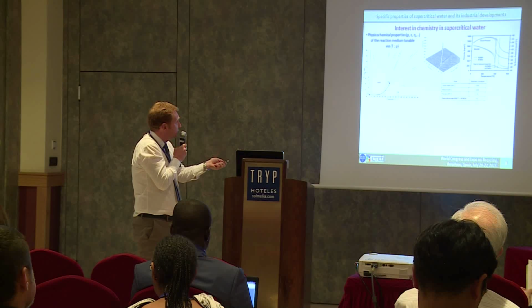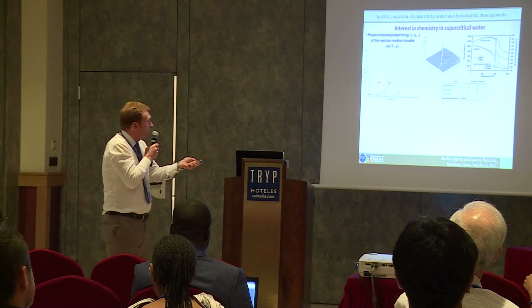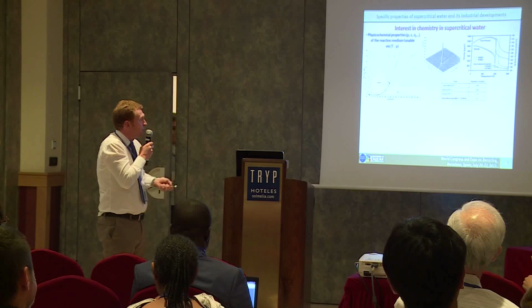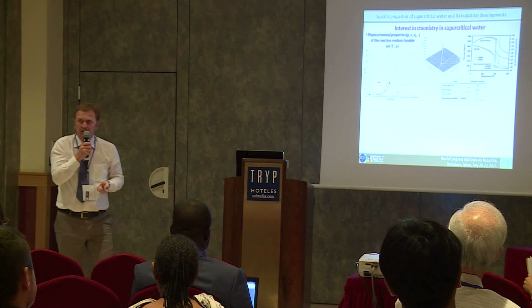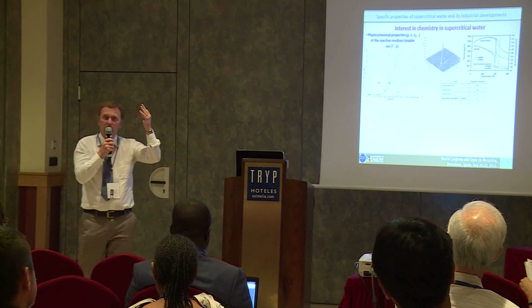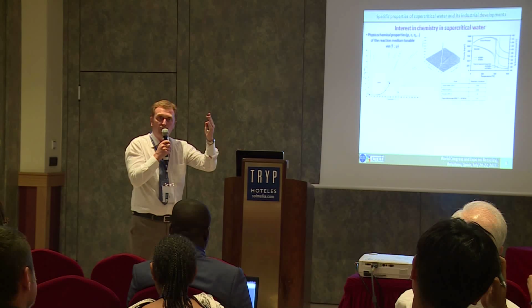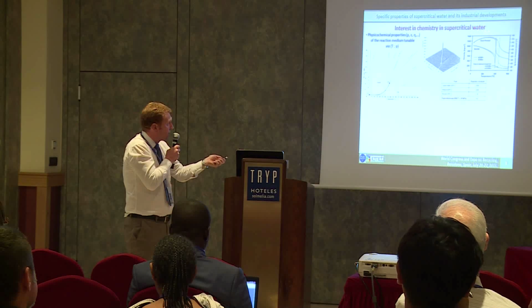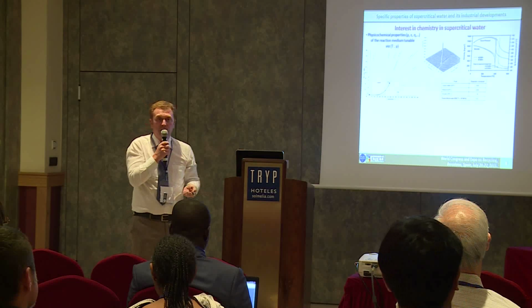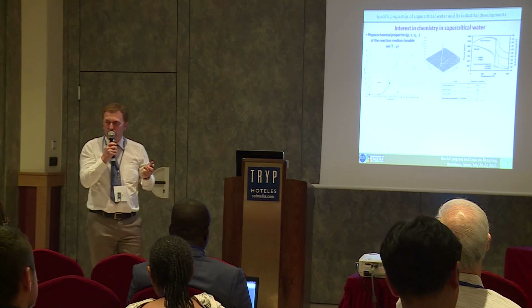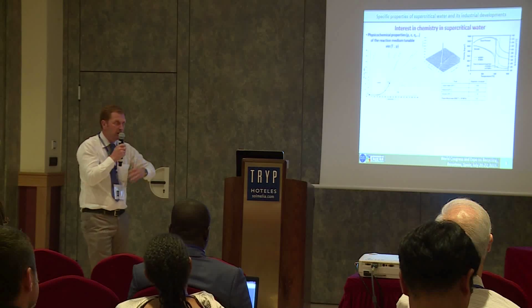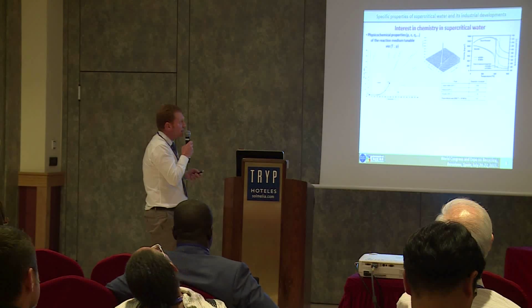So you know, 10 to the power minus 14, and if you increase temperature, you are reaching 10 to the power minus 11. This means 3 orders of magnitude higher than the one of water at room pressure and temperature. And after, when you are crossing the critical point, it falls down to 10 to the power minus 24. So this means you can play with chemistry around.